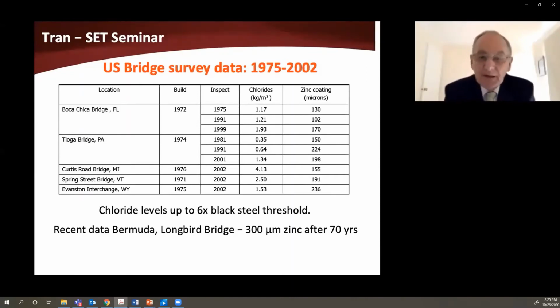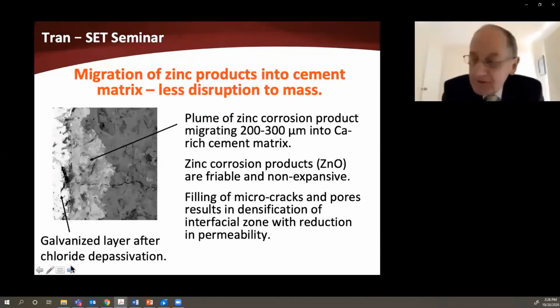Now, just recently, a bridge in Bermuda was demolished. It was the Longbird Bridge. It was demolished because it was badly damaged in a hurricane and needed to be replaced. Some steel samples from that were recovered. After 70 years of exposure, this bridge having been demolished earlier in 2020, there was still 300 microns of zinc left on the surface. Remember, the ASTM requirement is a minimum of 85 microns of zinc. So what this is showing is that in the field data, zinc can tolerate these very high levels of chloride without any significant effect.